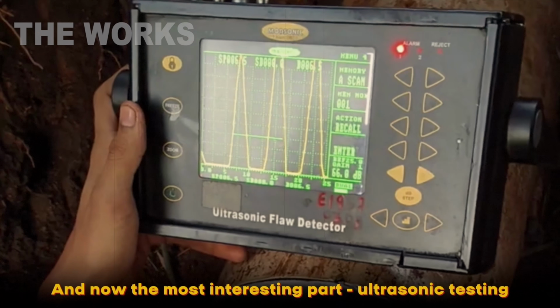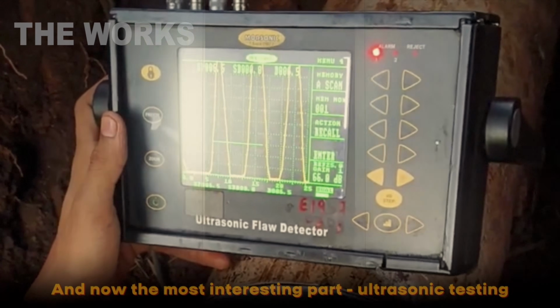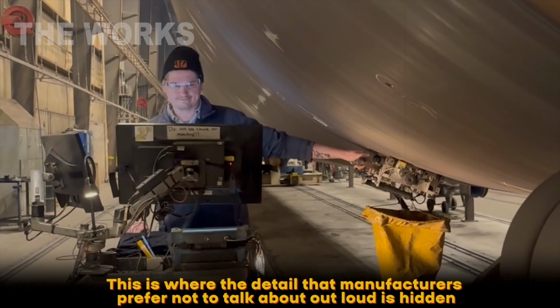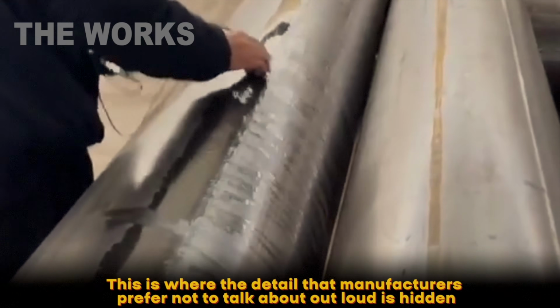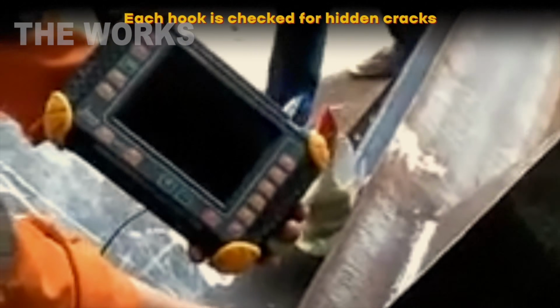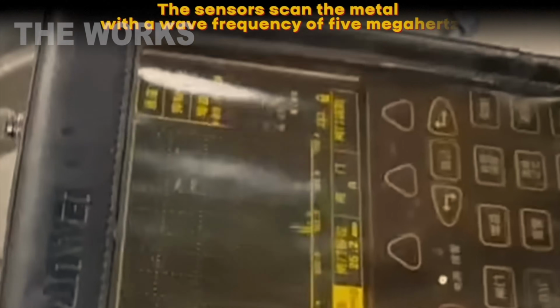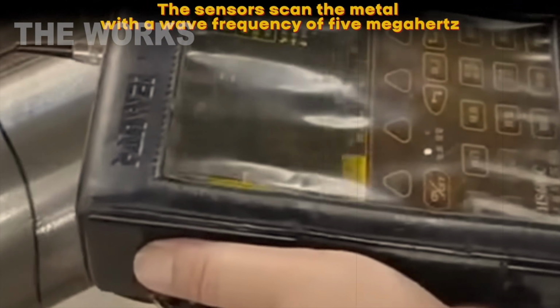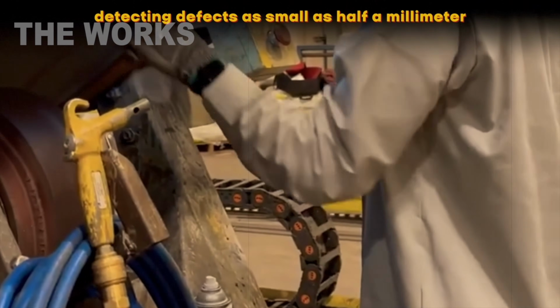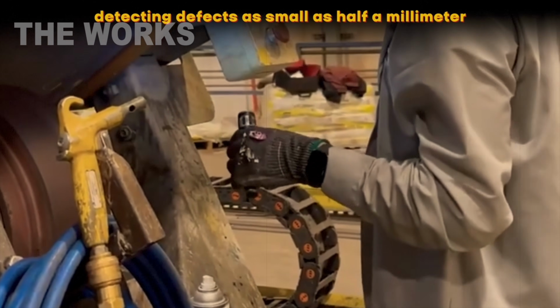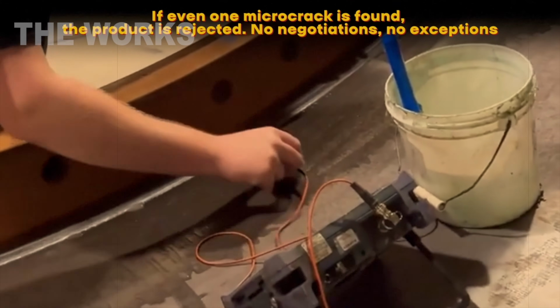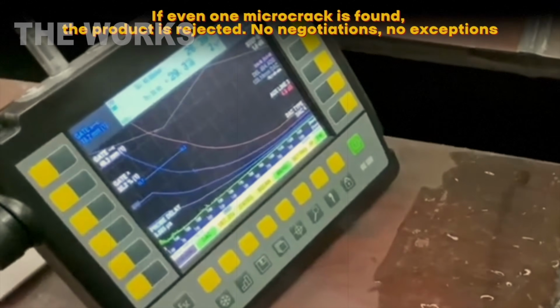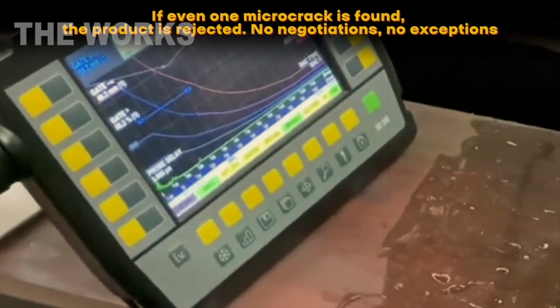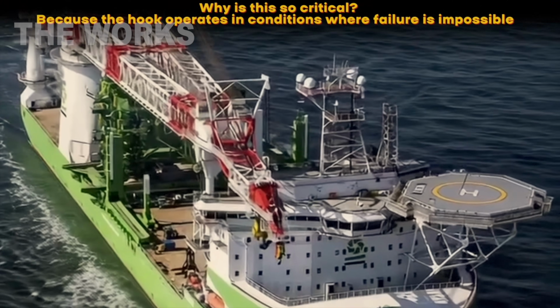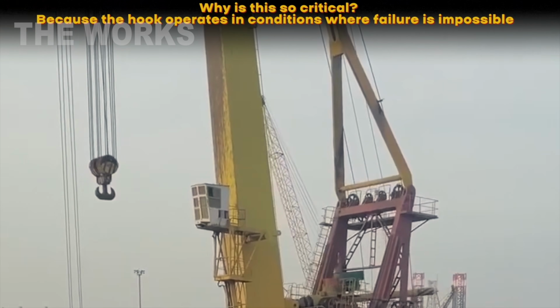Now here's where it gets really interesting: ultrasonic testing. This is where manufacturers hide a detail they'd rather not talk about. Every hook gets checked for hidden cracks. Sensors scan the metal with a 5 MHz wave, detecting defects as small as half a millimeter. If even one microcrack shows up, the part gets scrapped. No negotiations, no exceptions. Why is this so critical? Because these hooks work in conditions where failure isn't an option.